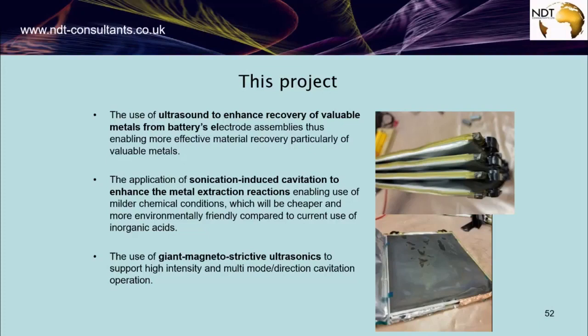The first step is that we use ultrasound on electrode material to extract the active material, which is the lithium, cobalt, manganese, or depending, batteries have different compositions, but let's talk about, for example, a simple battery, which is lithium cobalt oxide. Then this active material is bound to the electrode metal using an organic adhesive, and this one is very strong. And one of the reasons the recycling methods now shred the whole electrode is because it's difficult for them to break that organic adhesive that binds the active materials to the metal.